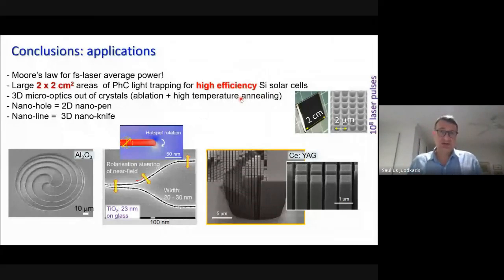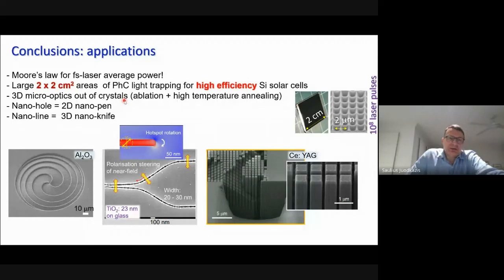I showed calculations for 1 micron, it's just calculations, but this separation of carriers is even better for very thin solar cells. So if we make light trapping using femtosecond writing, it can be something practical. Then micro-optics out of crystals. Again, not the first idea you will try. You think that glass is easier, but if you want to fabricate very complex shapes which are not damaged by high temperature annealing, and then they are maintaining shape for optical function, crystals actually can be very useful.